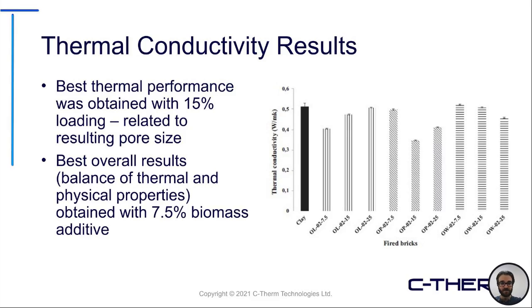And then through the study of the thermal conductivity, they were able to hone in on the best performing thermal sample. So this was obtained with a 15% loading. And they found that related to the ideal pore size that was generated during the firing process of that brick. But even though that 15% loading resulted in the best overall thermal performance, when taking in other considerations such as the physical and the acoustic properties of that sample, the overall best performing sample was the 7.5% additive.